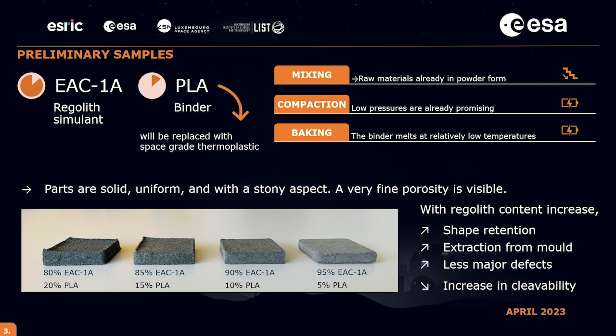So you can see in the picture that in one of the preliminary activities we performed, we went from 20% of PLA to 5% of PLA, and we always obtain parts which are solid, uniform, and with a stony aspect. We also noticed that the shape retention improved with the regolith content. It was also easier to extract them from the mold, and we also got fewer major defects.